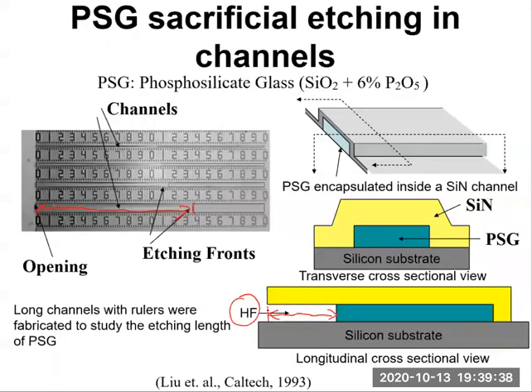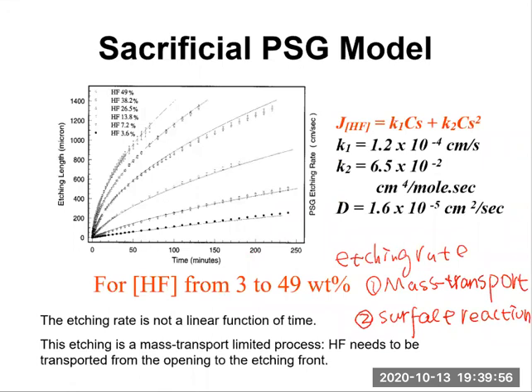First, HF needs to be transported to the etching front. Mass transportation. Then second, HF needs to react with PSG at the surface. So these two processes occur in series, and the etching rate is determined by the slower process. In this case, mass transportation is slower, so the etching rate is determined by the mass transport, and the etching rate decreases over time.